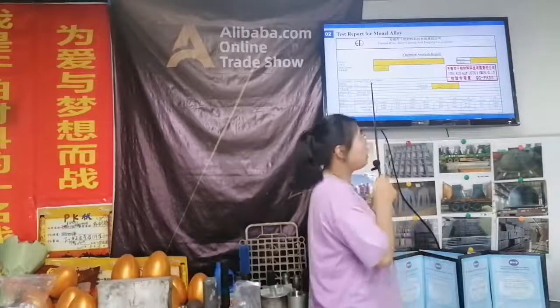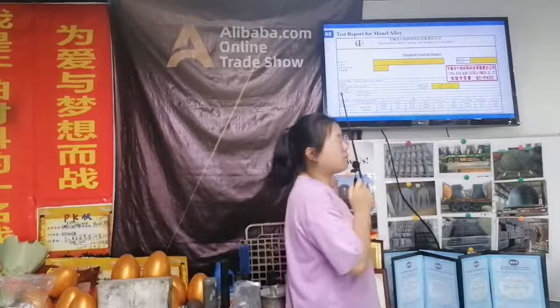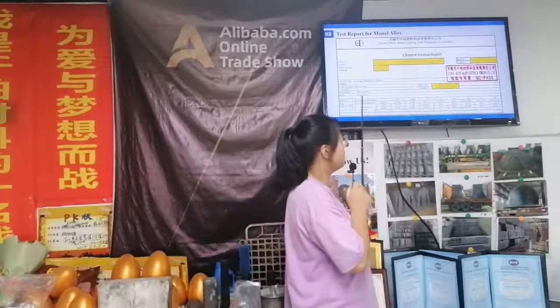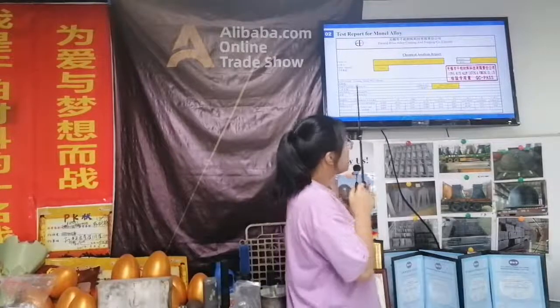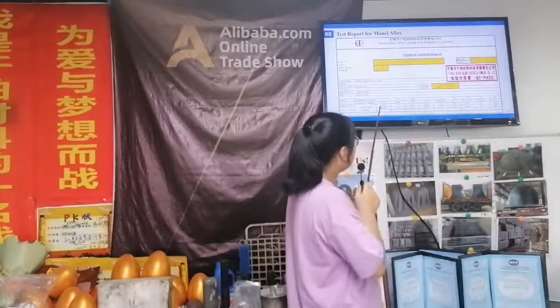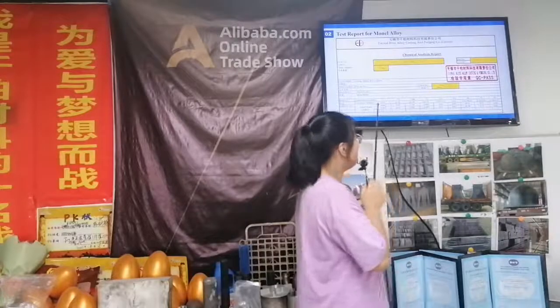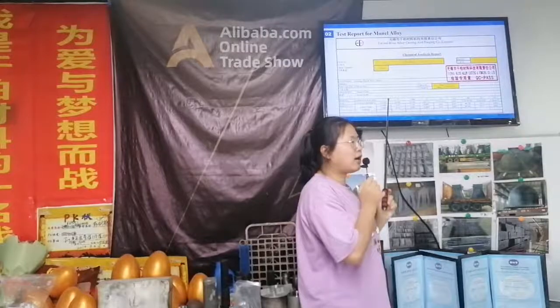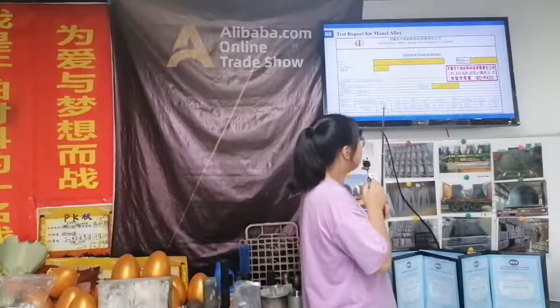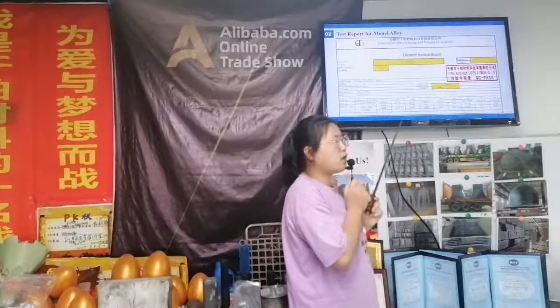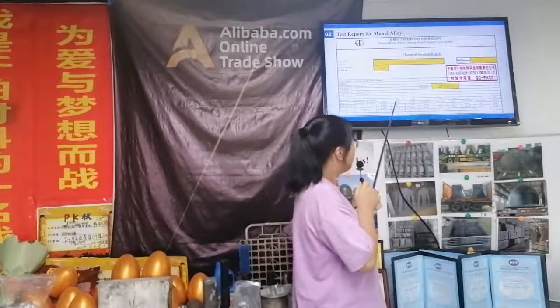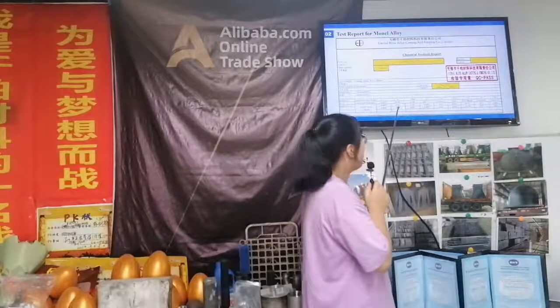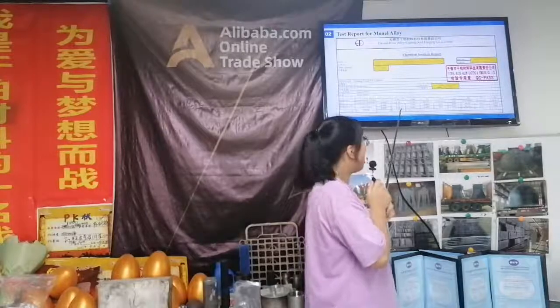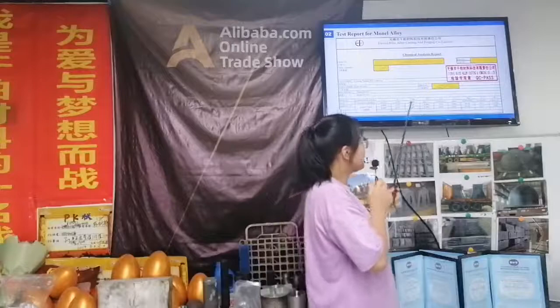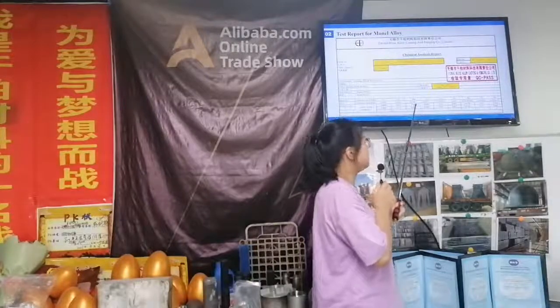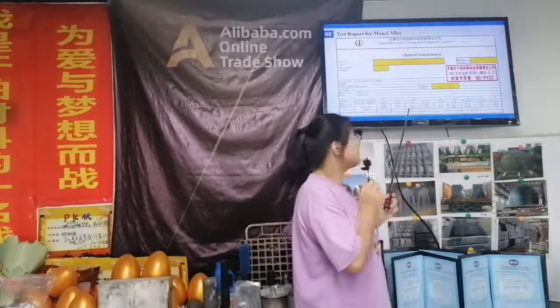Next, test report for monel alloy. You can see the material is Monel K500. The product is bolt. You can see the chemical composition. For carbon, the range is less than 0.025%. The actual value is 0.008 or 0.009. For silicon is less than 0.5%. The actual value is 0.37 or 0.23. For manganese, the range is less than 1.5%. The actual value is 1.14 or 0.95.